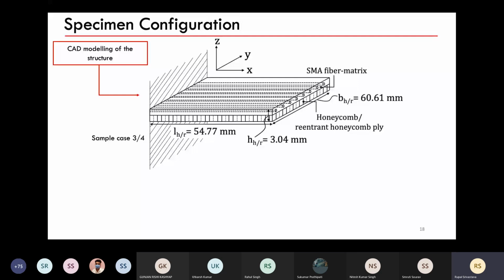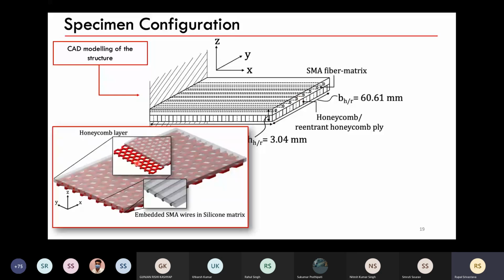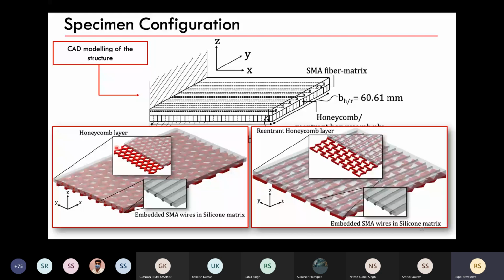Then we also thought of two interesting structures where one layer was embedded with shape memory alloy wires, and the other layer had a honeycomb or reentrant honeycomb ply. Honeycomb is basically like the honeycombs we know, and it was another ply in the composite. Reentrant honeycomb just means that the struts are bent inside instead of outside. If the struts were not bent inside, they would be a honeycomb structure, right? Now that they are bent inside, they are reentrant honeycomb structures, and these make auxetic structures, which we'll discuss later in this presentation.